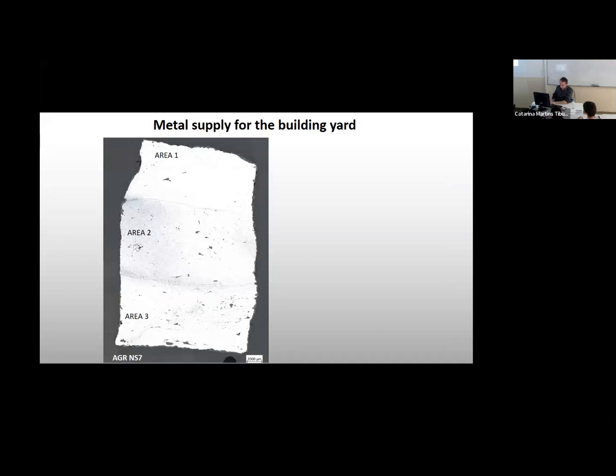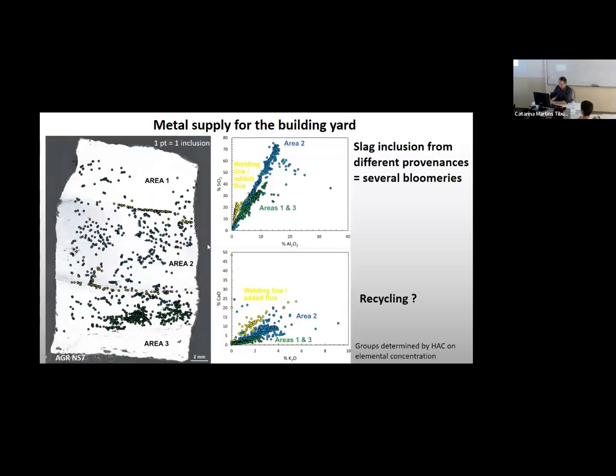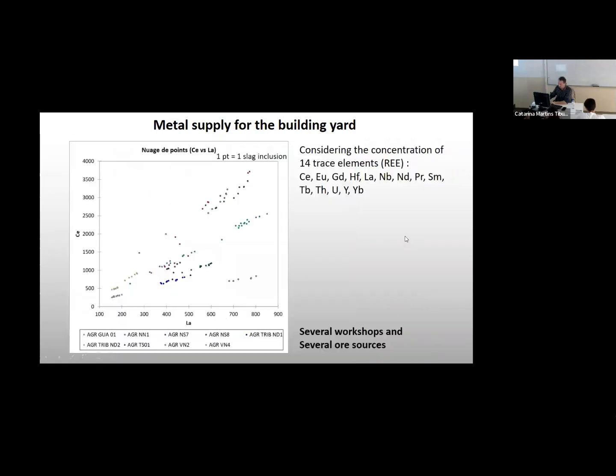So the first thing we did is that we analyzed these trunks that had some welding lines to see if the welding was between different kinds of materials or not. And that's how it turned out. Here you see the blue area in the middle. Every dot is one analysis of one slag inclusion, as you can see here. And so the blue dots are aligned for this middle part, and the two others are aligned with a different alignment, which means that here we have what is called a classic weld. It's like you open one bar, you stick a bar in the middle, and then you hammer it. So you have the same bar on top and bottom, and a different bar inside. And you can also see that there are some add-ins which have a different composition for the flux that was made during this welding. So still, is that recycling or not? I'll try to go into this question.